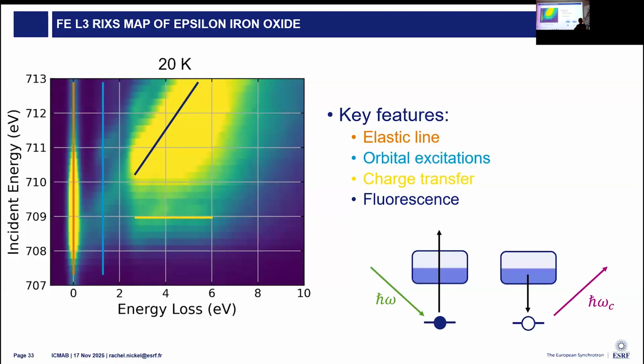The fluorescence I haven't discussed before, but we have the excitation of the core hole, not into the valence band, but into the continuum. And then the filling of the produced core hole from the valence band. And this gives us our characteristic X-ray. This is a little bit different than the other excitations where we had a fixed energy loss. Here, the energy emitted is constant. And so as we change the incident energy, it shows up as a diagonal streak across our spectrum.